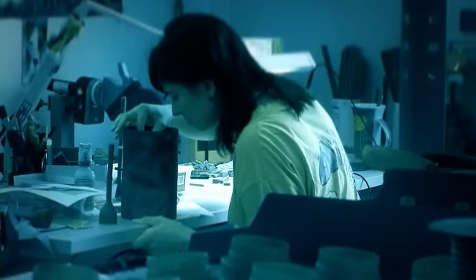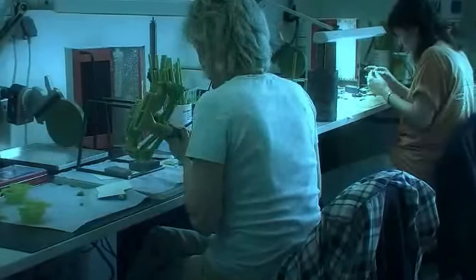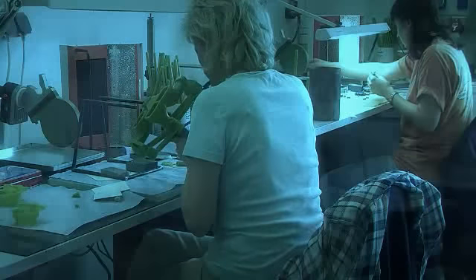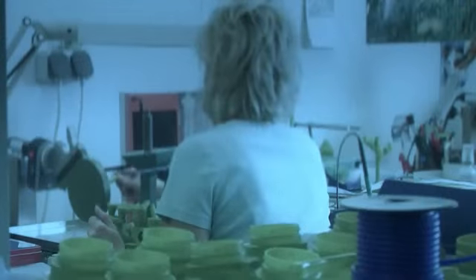Later, the stem and branches of this wax tree form the channels for the flow of the metal in the casting process. Special expertise is required to ensure an uninterrupted flow of the molten metal which is necessary in feeding the cast part. This is crucial for good filling and high quality. The caster is checking the wax trees thoroughly, especially the surface quality and the stability of the spruing. From the weight of the wax tree, the caster calculates the weight of the metal to be melted and cast.